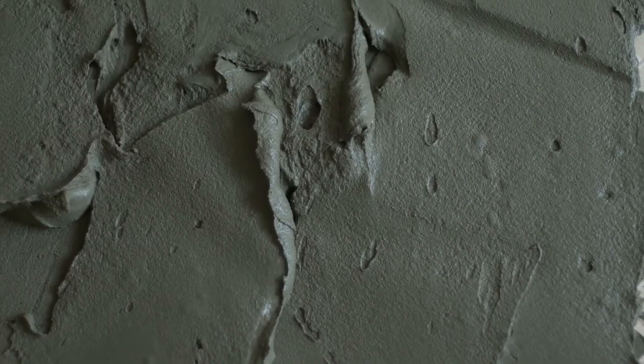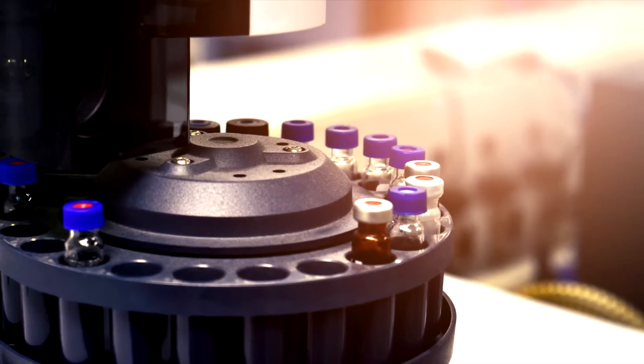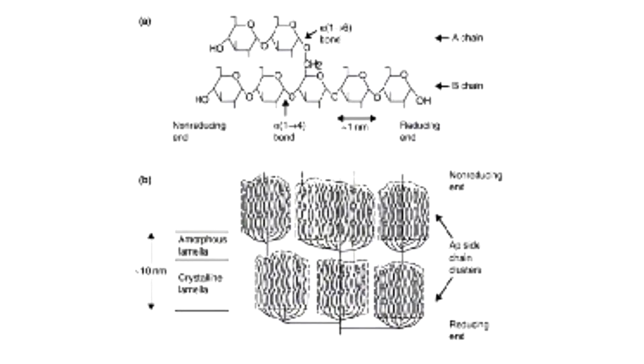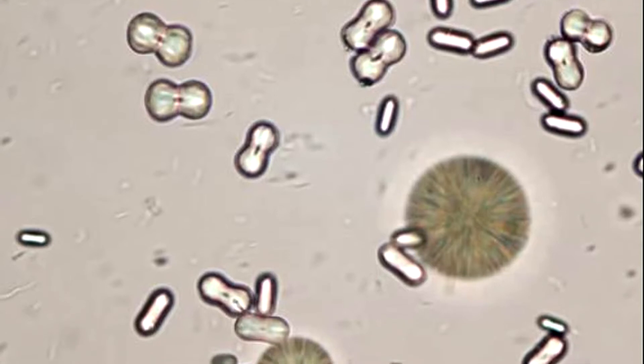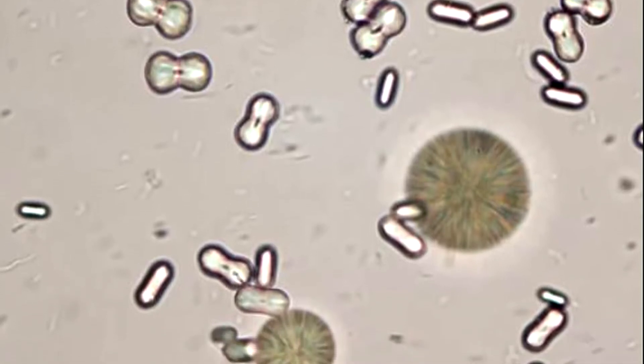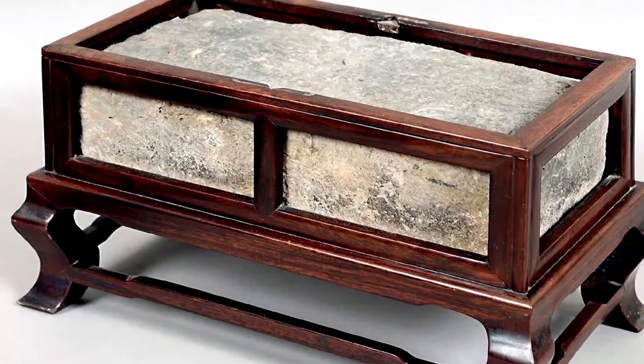What was surprising were the physical and mechanical properties the sticky rice gave the mortar. Using a scanning electron microscope and chemical analysis, they found that the addition of rice's amylopectin to lime's calcium carbonate created smaller calcium carbonate crystals, producing a more tightly bonded mixture that was more likely to hold its shape over time and more water-resistant.